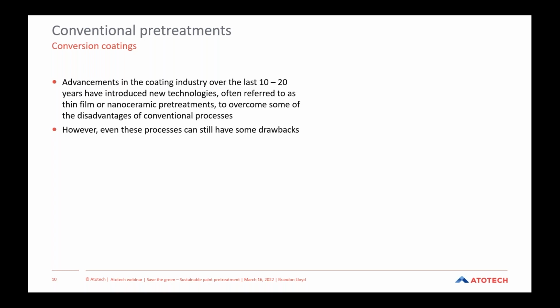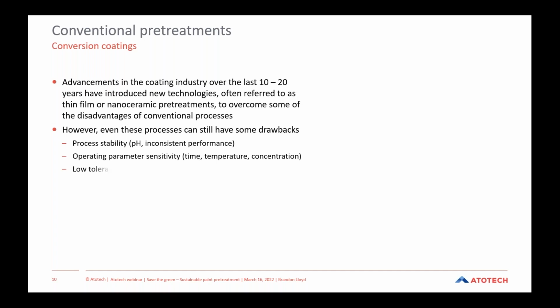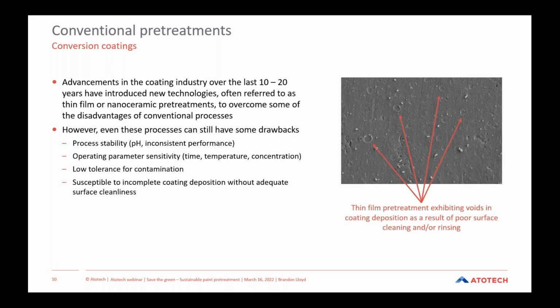However, these processes can still have some negative aspects associated with them. Those include process stability concerns, operating parameter sensitivity, whether we're talking about time, temperature, or concentration, and a low tolerance for contamination. They can be susceptible to incomplete coating deposition without adequate surface cleanliness. And as we discussed, cleaning is the essential first step. And on the right side of the page here, you can see an example of a thin film pretreatment that is exhibiting voids in the coating deposition itself as a result of this poor surface cleaning and/or poor rinsing.